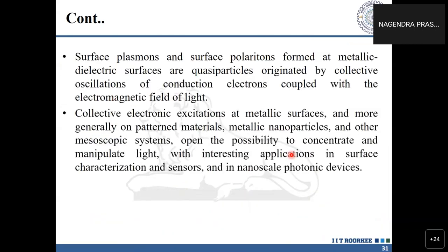So surface plasmons and surface polaritons formed at metallic dielectric surfaces are quasi-particles originated by collective oscillations of conduction electrons coupled with the electromagnetic field of light. Collective electronic excitations at metallic surfaces and, more generally, on patterned materials, metallic nanoparticles and other mesoscopic systems open the possibility to concentrate and manipulate light, with interesting applications in surface characterization, sensors and nanoscale photonic devices.